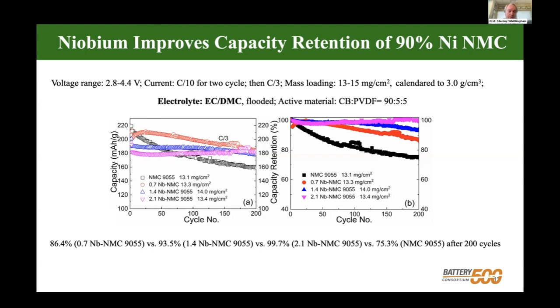And you can see the capacity of the niobium-free material falls the fastest. This is the black one here. The one with 0.7, we have some wetting issues here. It falls off less rapidly. But the challenge in these carbonate electrolytes is the capacity. You'll notice as we put more niobium in, the initial capacity is dropping.